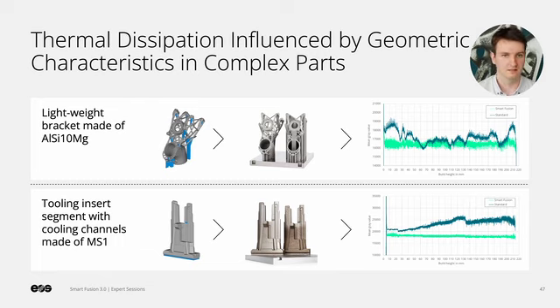In the MS1 tooling insert, the gray value plot is more straightforward. Heat is accumulated during build-up until a maximum of around 26,000 gray values is reached. With an initial value of about 20,000, this marks a 30% increase. The bump at around 120 mm can be explained by the overhang in the center of the part. It is typical for MS1 that excessive temperatures, like we see here, are accompanied by tempering colors on the part surface. You can see this in the slightly more brownish appearance of the sample built without Smart Fusion.